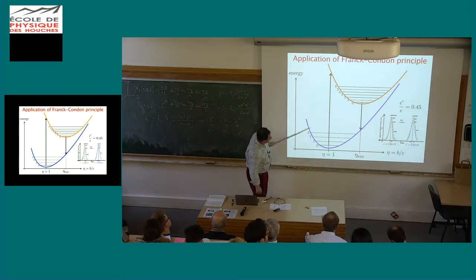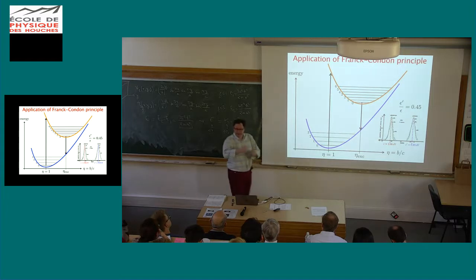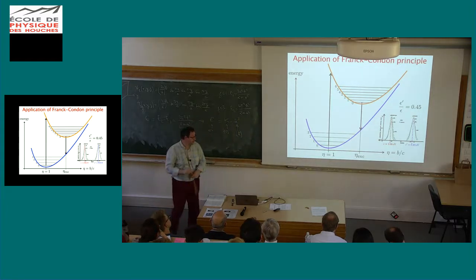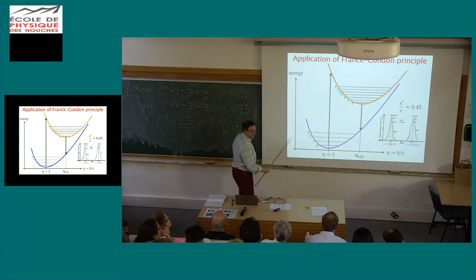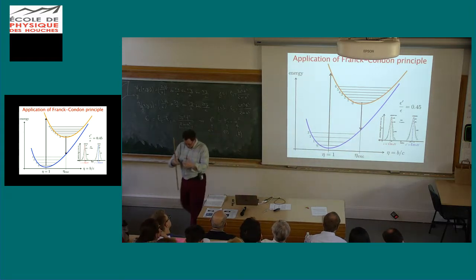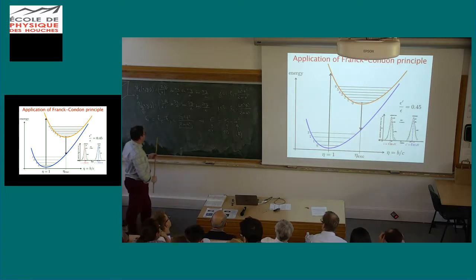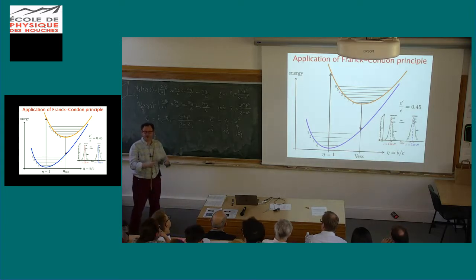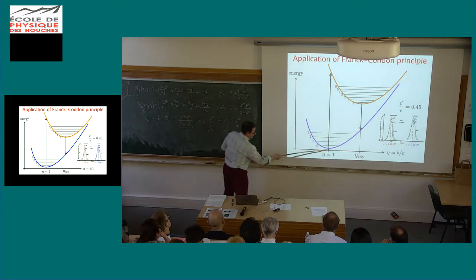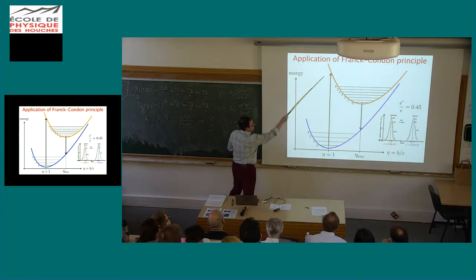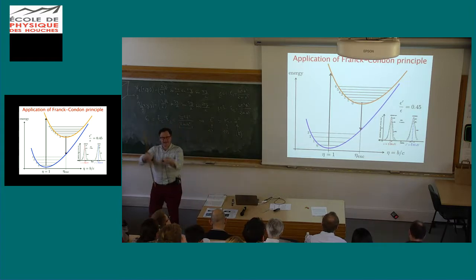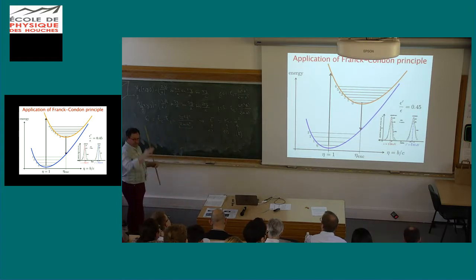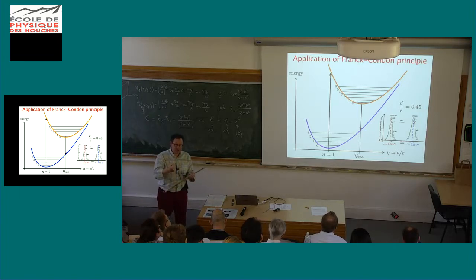We start from the quantization of the crystal vibration as a function of this parameter. From the ground state we have a perfect cubic symmetry, eta equal 1. Now we have transitions from all those levels. But when it goes to the upper level, it will not be the fundamental energy of this level. That means the system will distort.